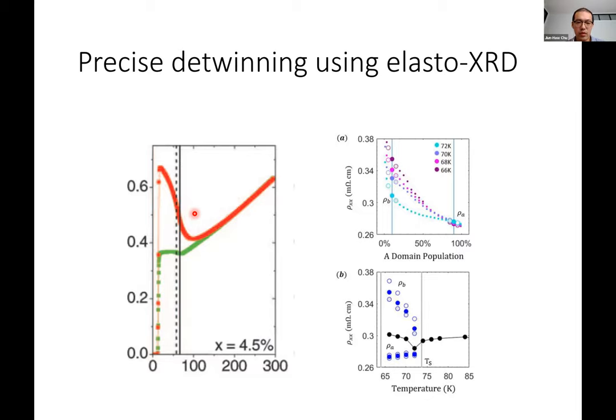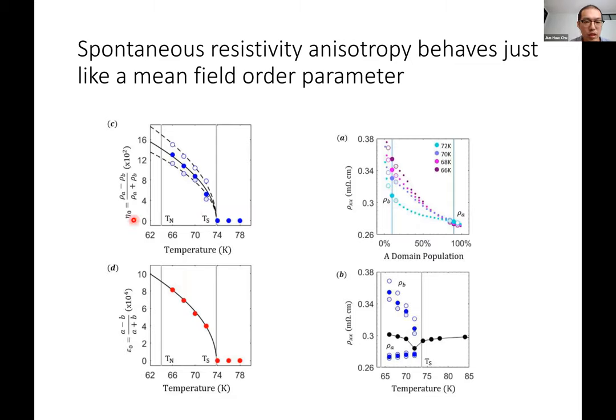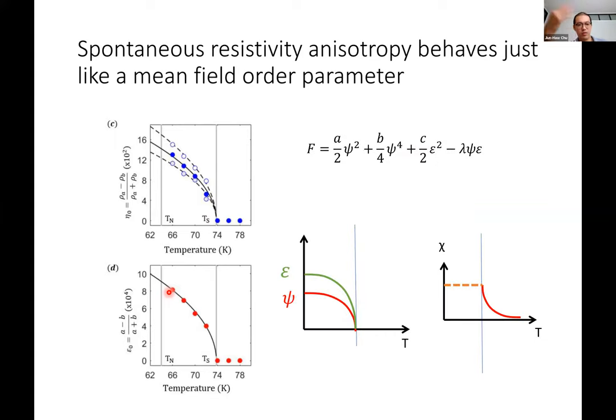So here we can really probe the spontaneous resistivity anisotropy and plot it as a function of temperature. We define the resistivity anisotropy as rho A minus rho B divided by rho A plus rho B. And it turns out that this temperature dependence looks just like a mean field order parameter, with a square root temperature dependence. This looks exactly the same as the structural order parameter, where the structural distortion also has a mean field-like temperature dependence. This same behavior is actually expected from the mean field derivation if you believe that resistivity anisotropy is a good proxy of the nematic order parameter.